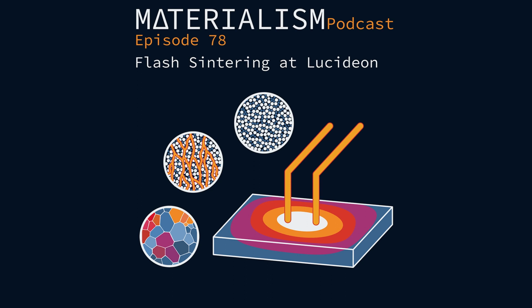So it can be 1 to 2 volts. It can be a couple of kilovolts. In comparison to SPS, it's not in a die, so the majority of your current is passing through the sample, not around the die. There's no applied pressure, although you can have applied pressure if you wish to. Therefore, we saw it as a more scalable solution in terms of size of part or multiple parts at once. But it's not like arc melting where you are directing the tip and melting your sample as you go.